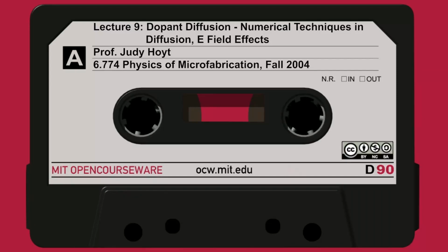C sub i on the left-hand side is equal to the concentration at time t, so whatever it was before, plus we add in this term on the right. That gives the change in the concentration in the ith slab after a time step delta t. And that term is just D, the diffusivity, times delta t divided by delta x squared, times the quantity in parentheses. Again, in order to evaluate it at any point C_i, all I need to know is the concentration at that point and the concentration of its two nearest neighbors.